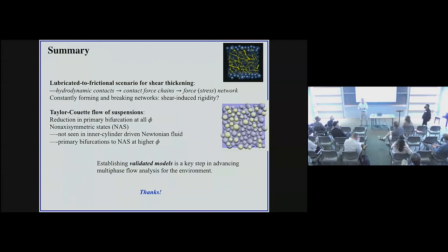So that goes back to Kimberly's question. If I don't have the repulsive force, then whether they're in contact is purely a geometric question. It doesn't have any stress dependence. But if there's a repulsive force, I'll come back to the origin, then the particles at low stress can slide past one another, keeping a liquid layer. If they're pushed hard, then the roughness elements can come into contact, and then you're frictional.